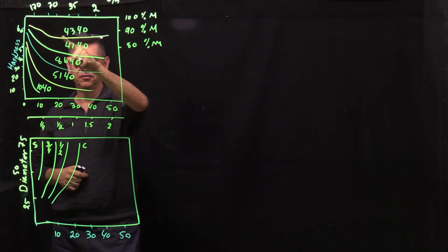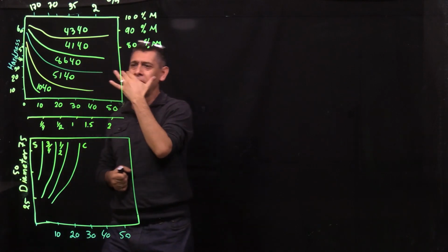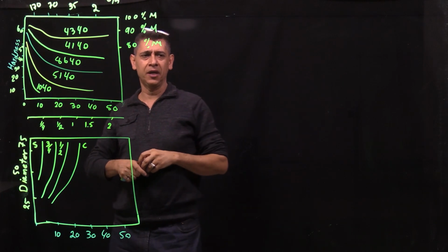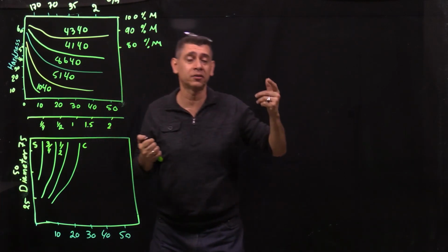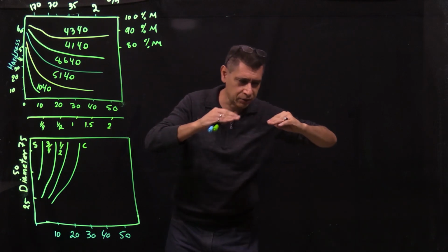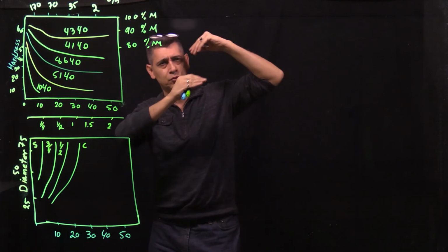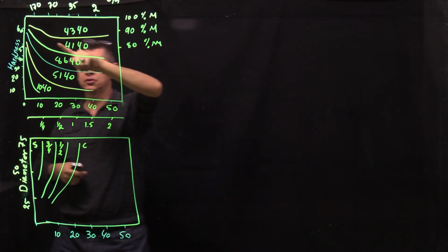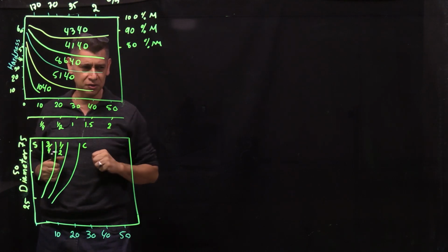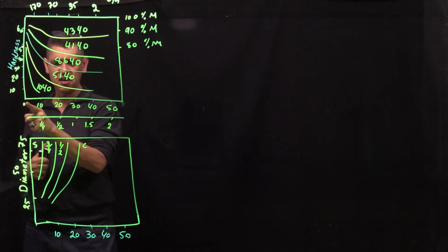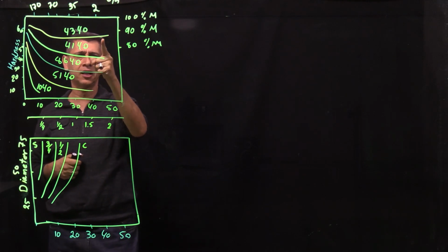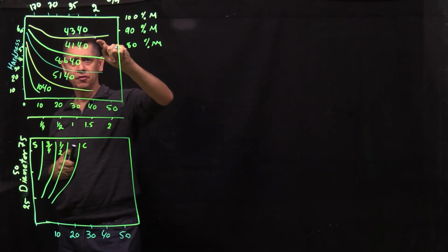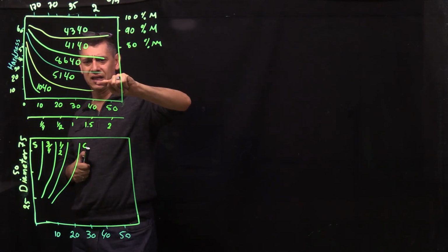So you can see that we have these alloys, and just by looking, you can say that the one that has less drop in the hardness means you get more martensite. You're not going to martensite, lower bainite, upper bainite, fine pearlite, and coarse pearlite. So it seems it has not been affected, or the majority of it is already martensite. So this is most hardenable. Even if I cool it very slowly, I still get plenty of martensite. So this is most hardenable, then less, then least.